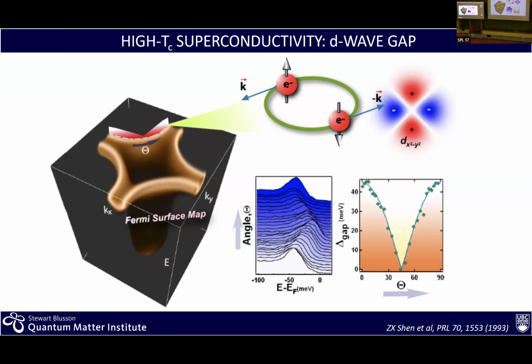But as you move along this Fermi surface, you move away from this peak. The peak doesn't stay at the chemical potential, which would be the behavior for a normal metal, but actually pulls back. It pulls away from the chemical potential. The pulling away is what we call the gap, and is a direct measure of the pairing. If we plot the position of this peak as a function of this momentum direction, which is along here, you can see 0, that's the node right in the middle. And as you move away, the gap gets larger to a maximum value here at the zone boundary. So this is really the magnitude of the pairing interaction in high temperature superconductors. And that's what we call the d-wave gap.